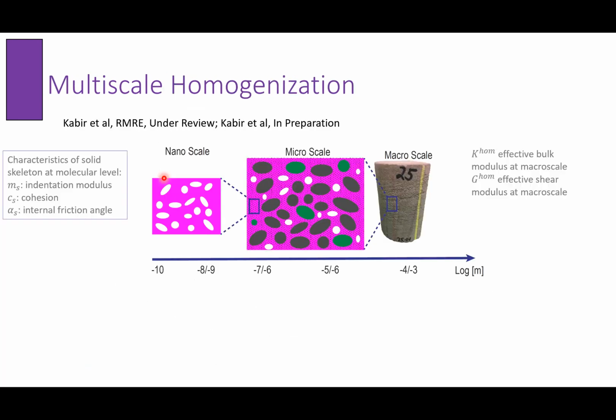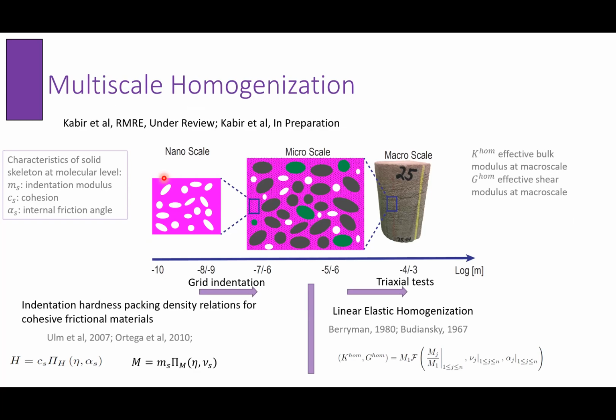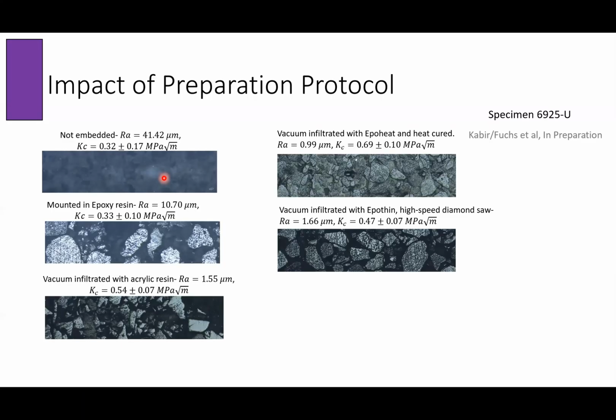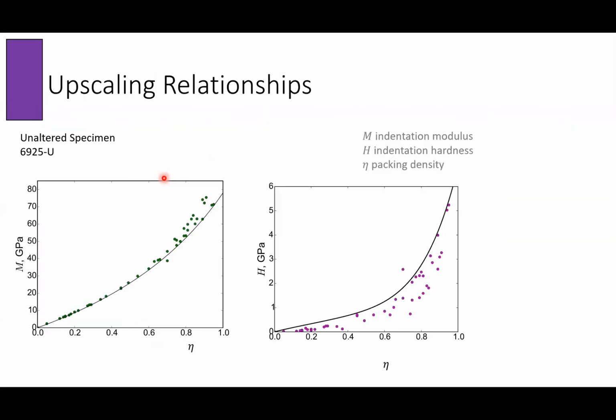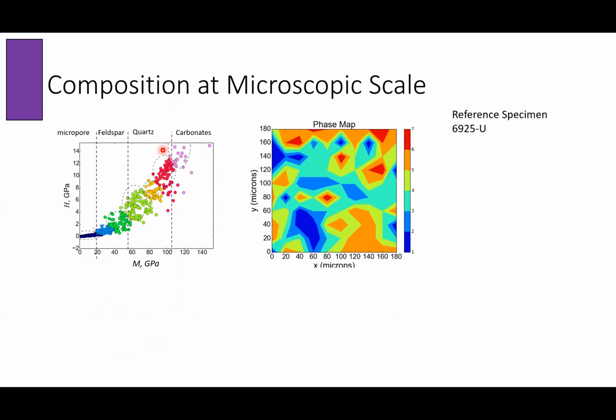Then the other way is when I'm processing my data. What I just said was to have boundaries, saying, for instance, carbonates, everything that is above 110 gigapascal, that's the carbonate. Quartz usually tends to be between 80 and 100 gigapascal, so this is where I'm going to put my quartz. And everything else that is at the level of 60 to 70 gigapascal, or up to 70 gigapascal, is going to be feldspar.